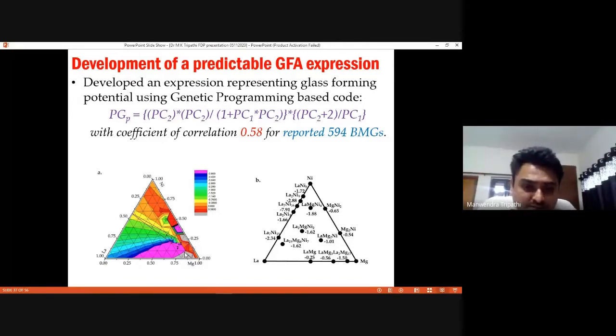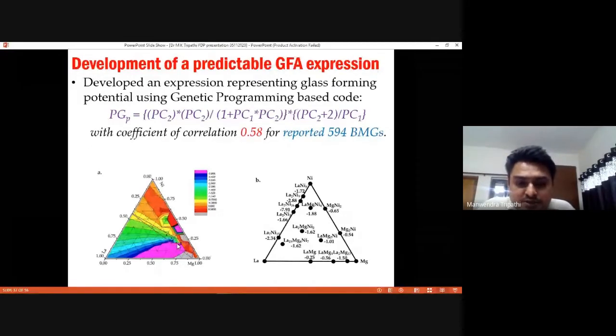And these black dots are the experimental synthesis. People have already done experimental synthesis. It is not done by us, but it is reported in literature. And we find that there is a good correspondence between the high GFA predicted and the synthesized compositions and this triangle, first. And second is that we have used the Materials Project data, and out of this ternary system, we are just trying to find out the stable compounds and we have picked their formation energy.